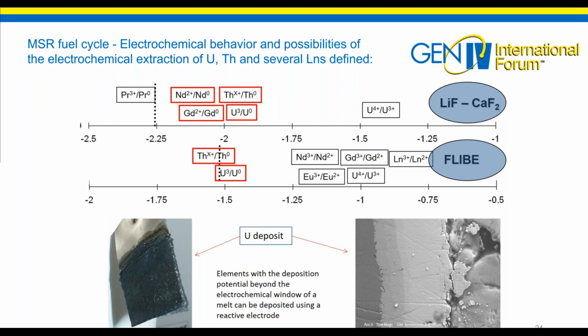In the picture, you can see the electrochemical potentials which were measured by UJV Rez for individual separation of uranium, thorium, and some lanthanides in FLiBe, and in lithium fluoride-calcium difluoride. For your information, the electroseparation method we used is linear potential sweep cyclic voltammetry. At the next slide,